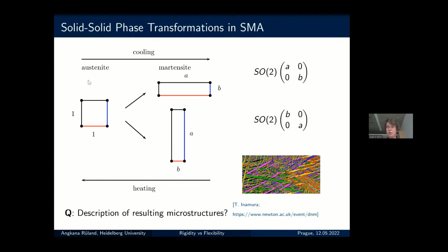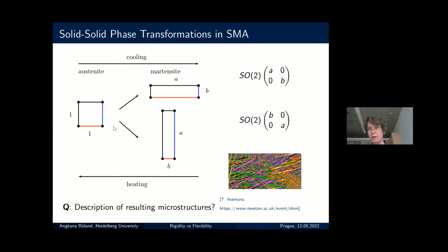Now, if you cool down the material, it transforms from this highly symmetric phase into a less symmetric low temperature phase, the martensite phase. And it does so by reducing symmetry, for instance, changing from this very symmetric high temperature lattice to a less symmetric low temperature lattice, for instance, this rectangular lattice, which it could do by elongating the red, compressing the blue line. But there's no reason why it should compress the blue line and elongate the red line, because it loses symmetry. You immediately have different variants of the low temperature state. You could just as well compress the red line and elongate the blue line, yielding in this case two different variants of this low temperature phase.